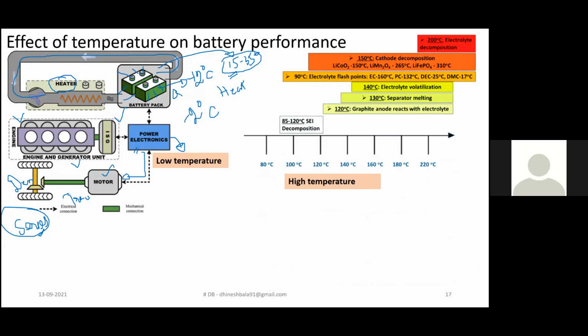And talking about high temperature condition, we are very much aware that the safety limit would vary from 60 to 70 degrees Celsius for lithium based batteries. Once you exceed 85 degrees Celsius, the solid electrolyte decomposition would start. We are very much aware of what the solid electrolyte layer is. It acts as an extra barrier on the rear side of your electrolyte, which would restrict the movement of electrons in the horizontal direction.